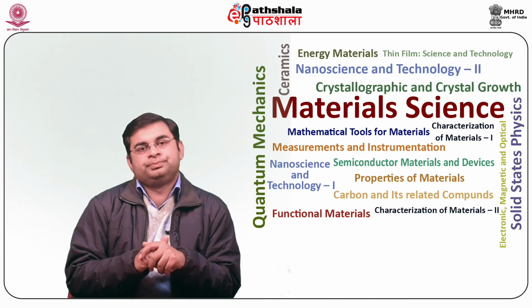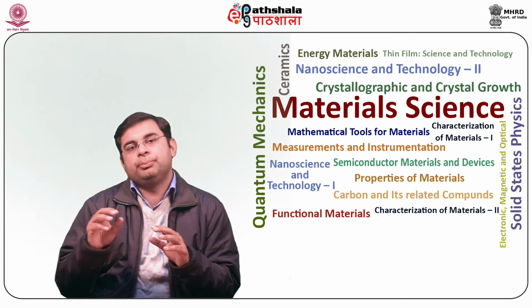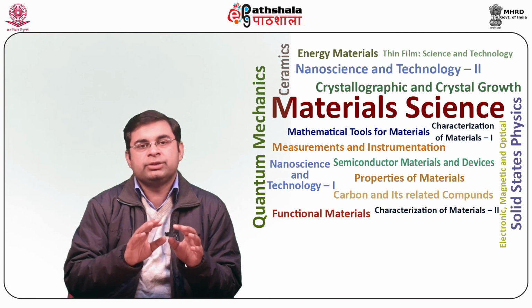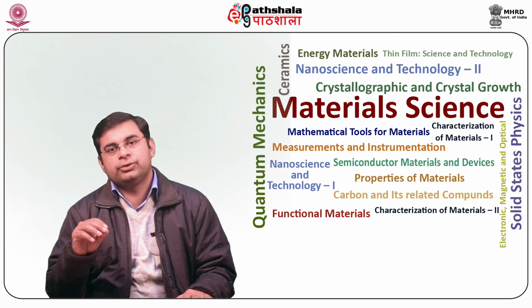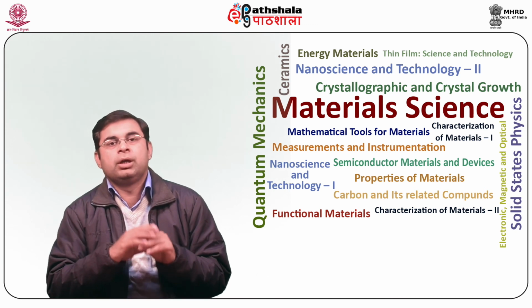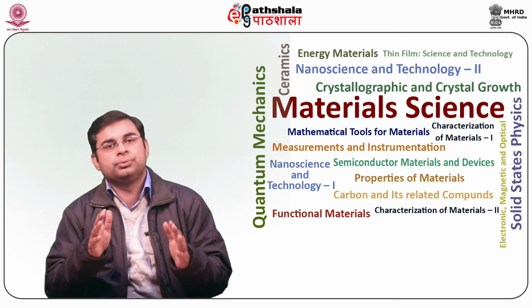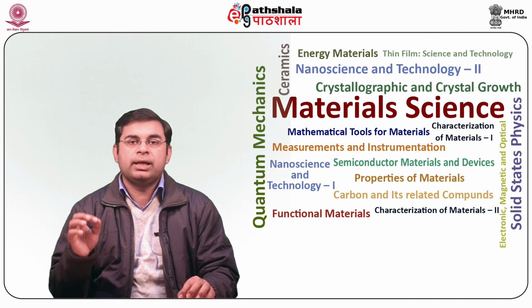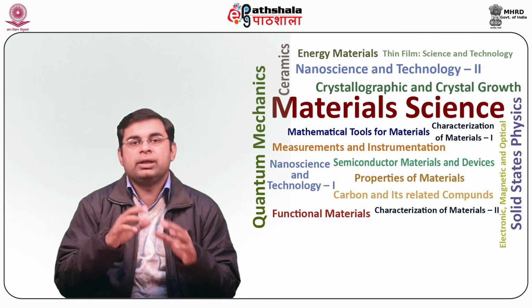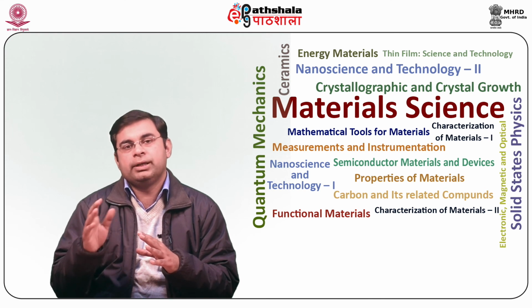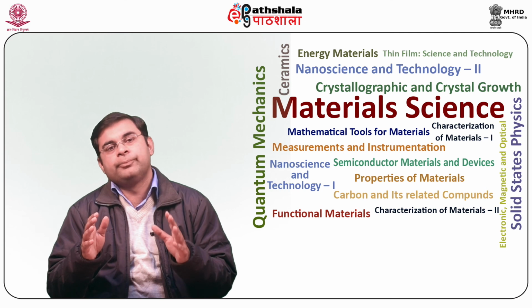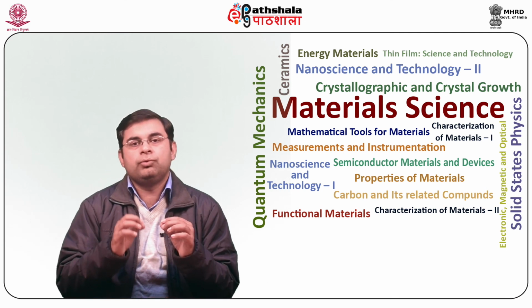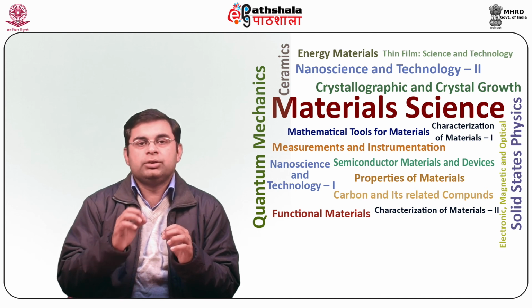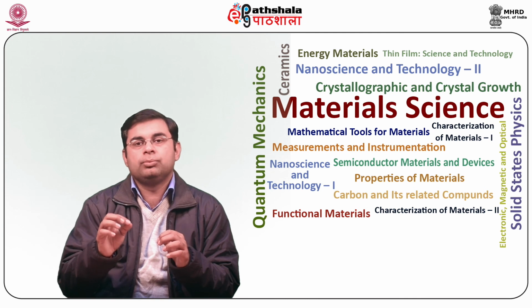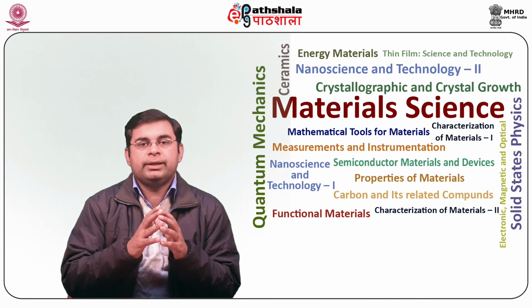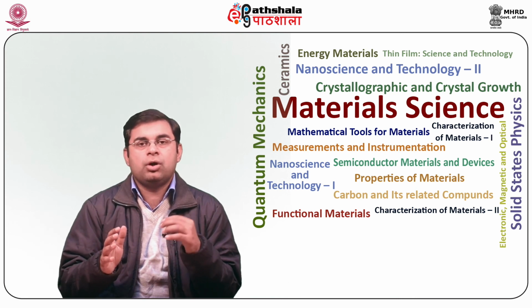Effect of band structure. Electron donating impurities generate additional states close to the conduction band, whereas the electron deficient acceptor impurities generate states close to the valence band. The band gap between these energy states and the closest energy band is termed the dopant site binding energy, or E_B, and is usually small. Due to small values of E_B, room temperature thermally ionizes almost all the dopant atoms and creates free charge carriers in the conduction or valence band.